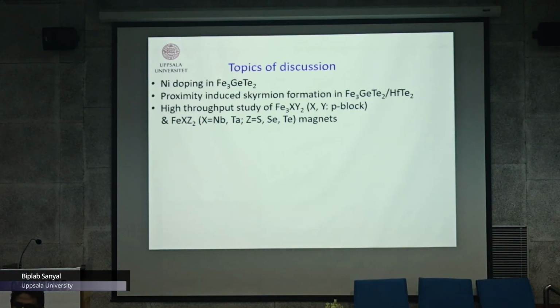Now this is a centrosymmetric system where we do not expect to see skyrmions. Nevertheless, some experimental groups have observed skyrmionic features in Fe3GeTe2. The reason is not entirely known; there are different theories about this. But we thought to make a heterostructure and look at certain scenarios to see whether there is a particular scenario where you can observe skyrmionic features. Because to observe skyrmionic features, you need a very critical balance of different parameters in your spin Hamiltonian.